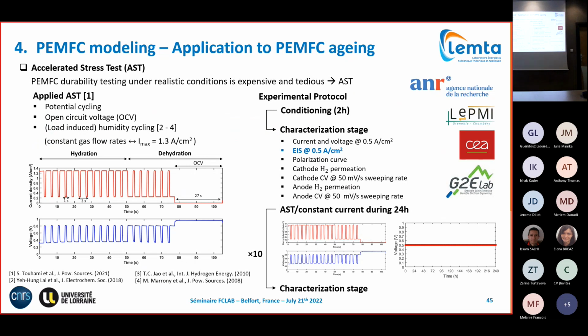So were you able to run any other tests on this cell after this 10 days? You mean to perform aging? Yes. We considered another presentation. I don't know if it's shown now or later. But yes, 10 days was for all our comparisons, and actually we succeeded in making pinholes and having an increase of the hydrogen permeation current, and yes. Exactly.